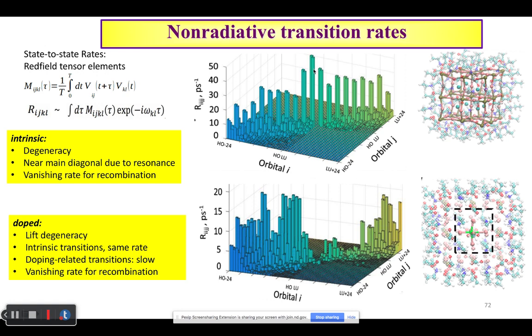We do not know if it is natural or an artifact, but the degenerate states have a very high rate of transitions between them. Probably it just goes back and forth, and smears out at the final state. But those high peaks are between degenerate states. Actually, how is your approach overall treating the degeneracy? Because usually you have really significant problems with degeneracy with surface hopping, for example. There are no problems with degeneracy until 20 picoseconds. Then numerical problems appear. I'm hiding these numerical problems from this presentation, but I have movies that demonstrate it.